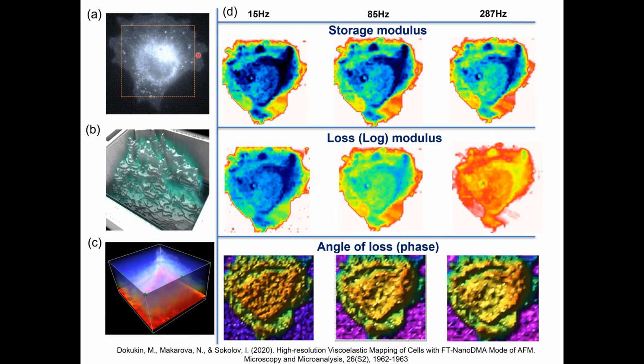This is an image of a cell. This is one of the HeLa cells. And you can see this optical image, not specifically labeled with any fluorescent molecule. And exactly this area shown here, imaged with AFM. And you can see that the optical image does not really correlate with this storage modulus distribution. So we have something which is definitely absolutely new. It is definitely one of the directions where we're trying to understand what exactly we are seeing here.